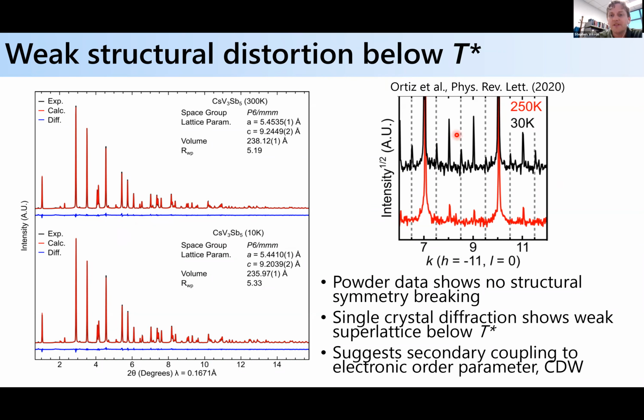But if you look very carefully with single crystal synchrotron X-ray diffraction, you find very weak structural superlattice peaks that are 4 to 5 orders weaker than the primary peaks that appear below this T star transition. And I think our initial take on this was it was suggestive of a secondary coupling to a primary electronic order parameter, something like a CDW, okay? That, combined with the susceptibility data, suggests that you might have a charge density wave phase in this system.